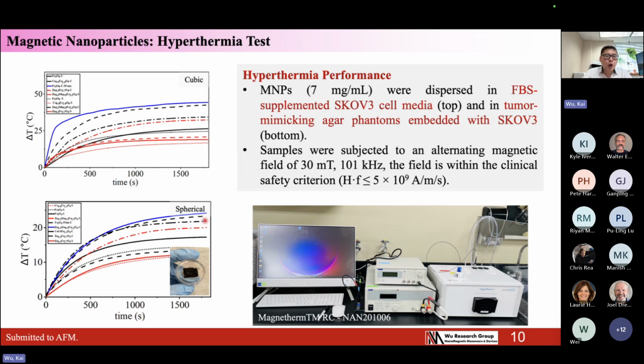So in any case, we only need the particles to heat up 10 degrees C to kill the cancer cells in the body. So all the conditions show us that the particles are very good candidates for hyperthermia treatment, in vivo and in vitro applications as well. I also want to mention that the AC magnetic field we apply for the hyperthermia treatment is within the clinical safety limit for the human body, which is 30 millitesla and 101 kilohertz, which is safe for in vivo use. Here's a photo of the system we use to calibrate the hyperthermia performance of these particles.